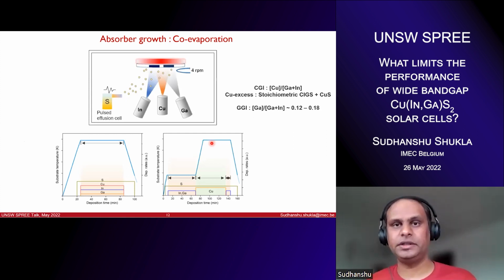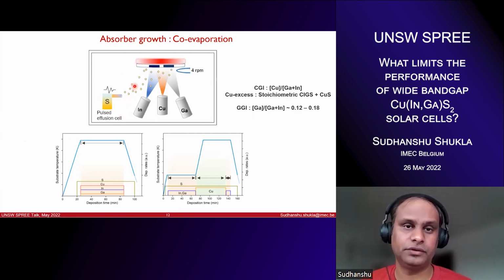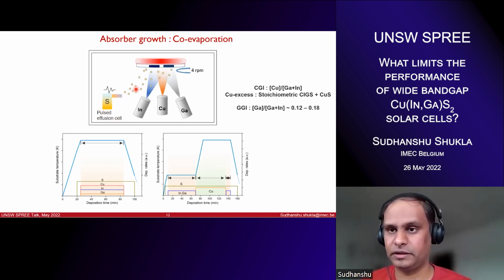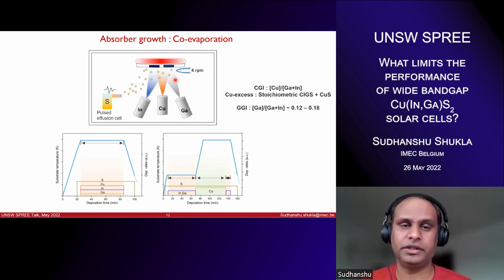So we adopted the strategy of co-evaporation, where we can make very nice high quality thin films, but there was a catch, a trick. Sulfur evaporation is not as straightforward as selenium, as it has a very high vapor pressure. So we deployed a custom made PVD chamber where we had a pulsed effusion cell of sulfur, where we can pulse it and control the sulfur flux as per our will. So we can have growth in high sulfur flux and growth in low sulfur flux. Although that is not the experiment that I want to show today, I just want to mention that we have done growth in such a chamber where we could control the sulfur flux.